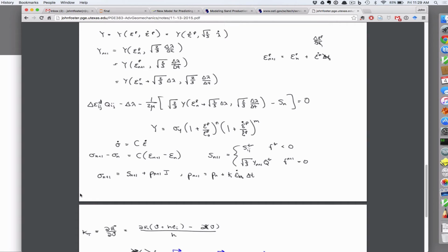It's a little more subtle than that. Okay, so you can have an initial if statement that checks whether it's above the quasi-static yield stress, or above the previous value of the yield stress, or below. If it's below, it's unloading and it's elastic. If it's above, then you might be plastic. The reason you might be plastic is because you're taking a step, and over that step, the yield surface grows, because the yield surface is a function of the plastic strain. So how can we update the epsilon p?